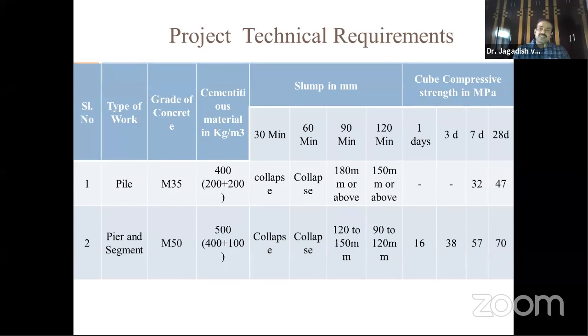Somebody may ask, sir, just now you told us 450 kg per cubic meter is the limit, but 450 kg per cubic meter is for cement only. You can use supplementary cementitious material up to 600, particularly if you take self-compacting concrete. The cementitious material can go from 450 to 600 kg per cubic meter. Here in this case, they've used 500 kg. Cement alone, they've used 400. The rest, 100, they've used GGBS.